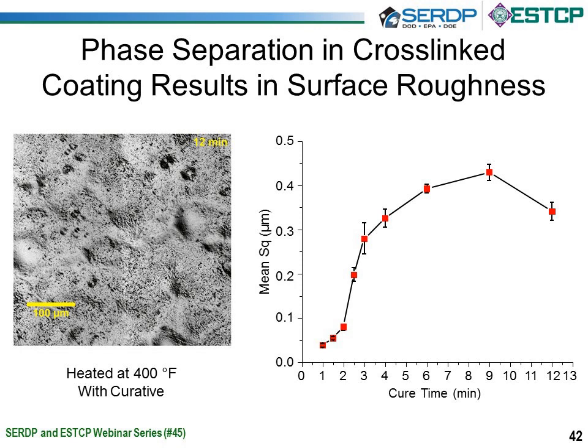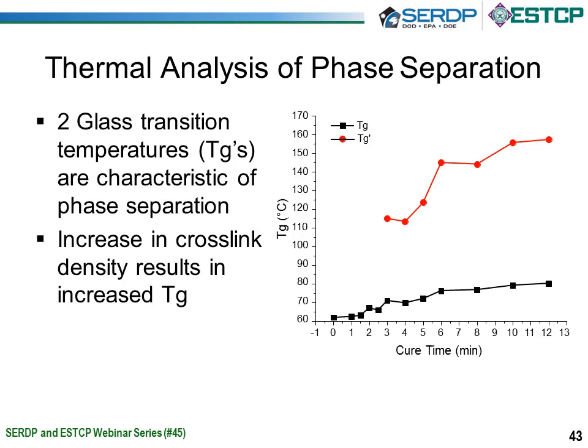Although we would like not to observe this reduced roughness over the 9 minutes, we realize that a very well cross-linked system is essential if we're going to achieve the desired chemical resistance. In addition to this, the continuous polymer film and being able to uniformly coat the surface is highly desirable. In slide 43, in order to confirm what we believe and had observed through surface roughness measurements, our attention turned to thermal analysis.